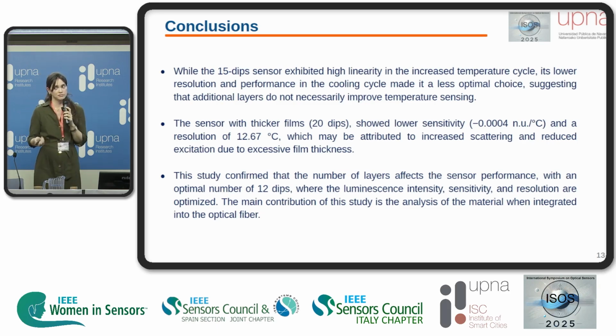And this study confirmed that the number of layers affects the sensor performance, with an optimal number of layers of 12 dips in our case, where the luminescence intensity, sensitivity, and resolution are optimized. And the main contribution of this study is the analysis once the material is integrated into the optical fiber.